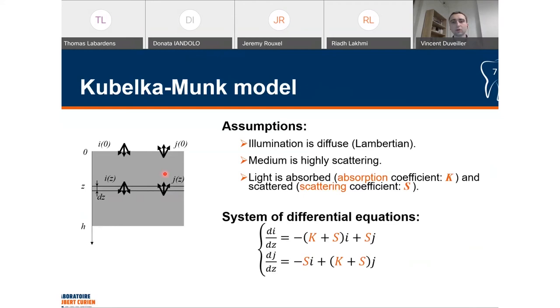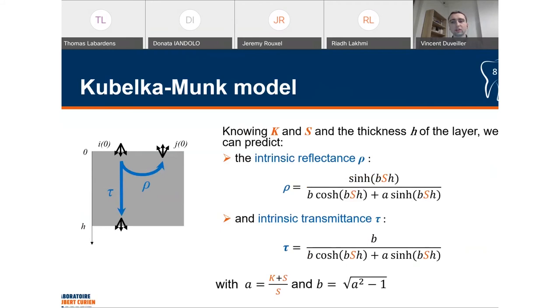It relies on several restrictive hypotheses: that the illumination is diffuse, that the medium is highly scattering, and that the light inside the medium is absorbed and scattered. The absorption coefficient is denoted K, and the scattering coefficient is denoted S. We can deduce these coefficients from measurements. Knowing these coefficients and the thickness H of a layer, the Kubelka-Munk model can predict the intrinsic reflectance, denoted rho, and the intrinsic transmittance, denoted tau, of this layer. These parameters are intrinsic to the layer because they do not take into account the light transfers occurring at the interface because of the change of optical index between the material and air.